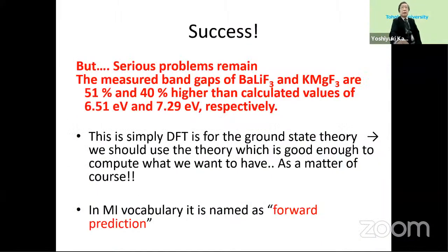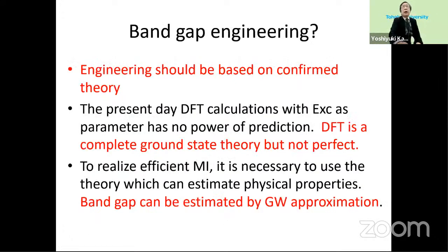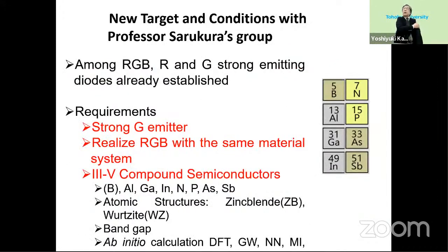So it's a kind of very good success, but the serious problem is that by DFT or any other phenomenological method, we cannot really predict the real band gap, the emission color. At that time, in the MI vocabulary, this was forward prediction, we compute. People said band gap engineering, but engineering should be based on confirmed theory. DFT is good for ground state, predictable atomic configurations, but not for the band gap. So we should shift to GW. The next subject came to us last year, and Mizuseki is working on that subject.